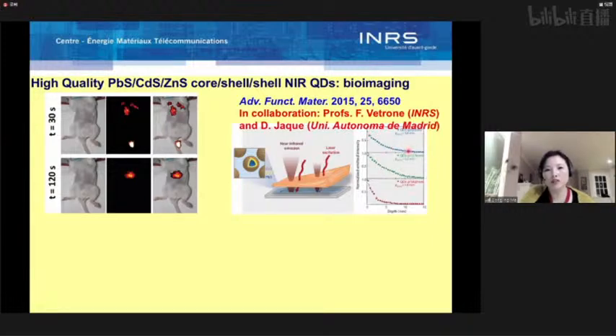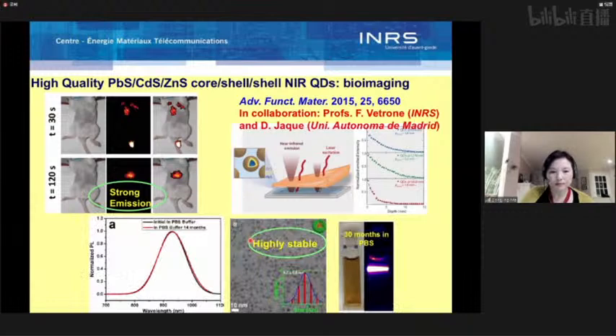Then we plot the photoluminescence intensity against tissue thickness. We found that for quantum dots emitting around 1270 nanometer, we can get the deepest penetration, over 1 centimeter, which is deeper compared to quantum dots emitting around 950 and quantum dots emitting at longer wavelengths, about 1450 nanometer. And also quantum dots are very stable. Here shows that after 14 months, the size has no change in PBS buffer, and for near-infrared imaging, after 30 months, the near-infrared intensity basically doesn't change. This image was captured by a near-infrared camera.